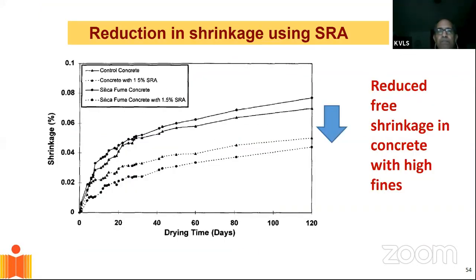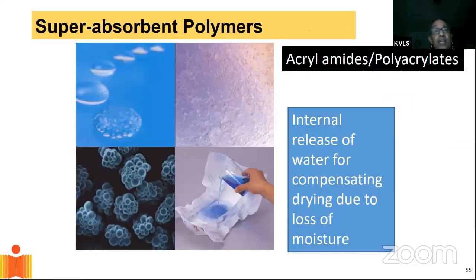And basically, I just want to show you here that if I add a small dosage, 1.5% the weight of cement in shrinkage reducing admixture, I'm able to reduce the shrinkage in concrete considerably, even with high fines present in it. So there are other kinds of technology we are borrowing to mitigate the risk of cracking. And this includes the use of super absorbent polymers. Super absorbent polymers are basically the polymers that go into making diapers. They basically absorb a lot of water and they hold on to moisture.